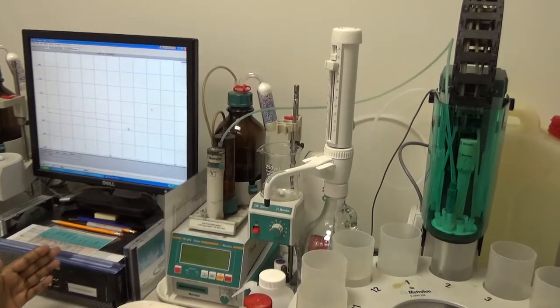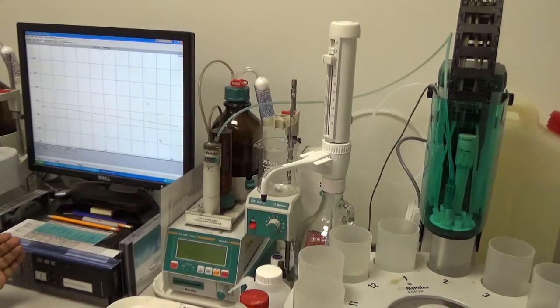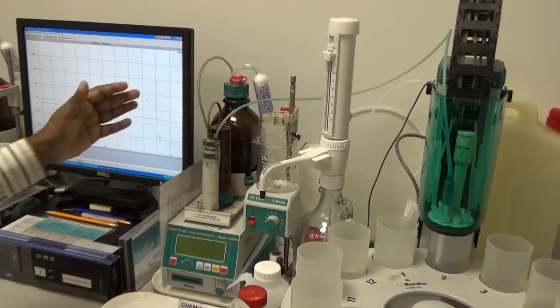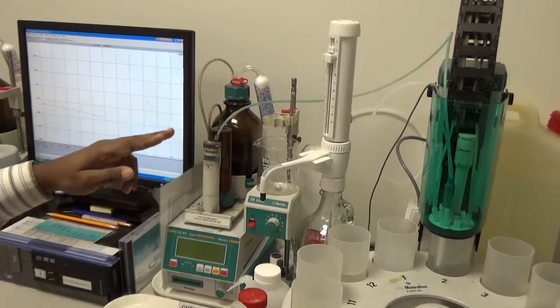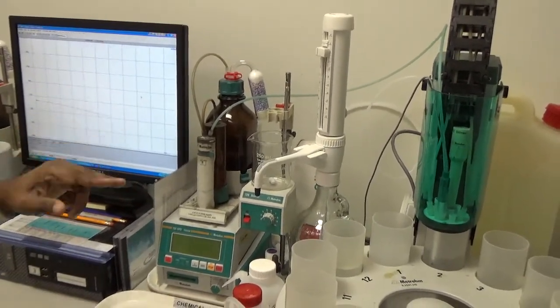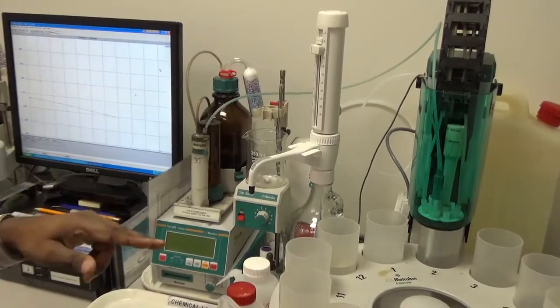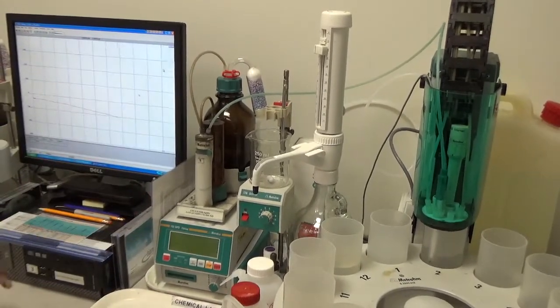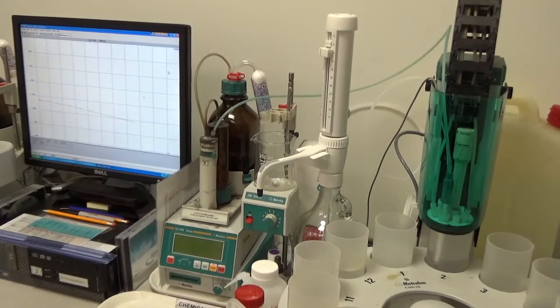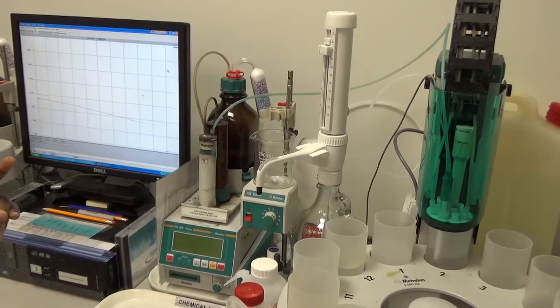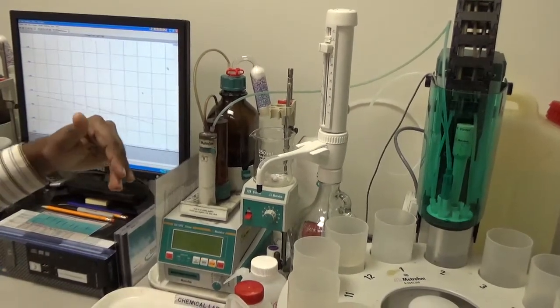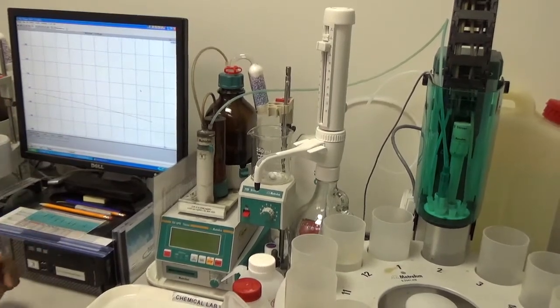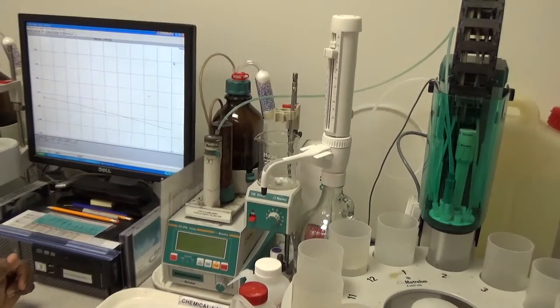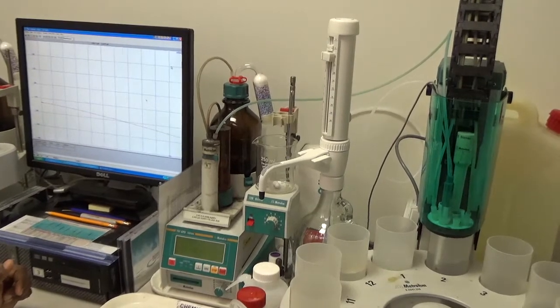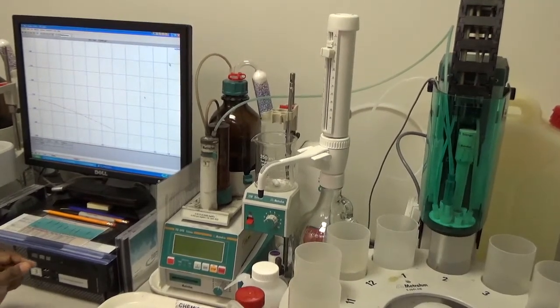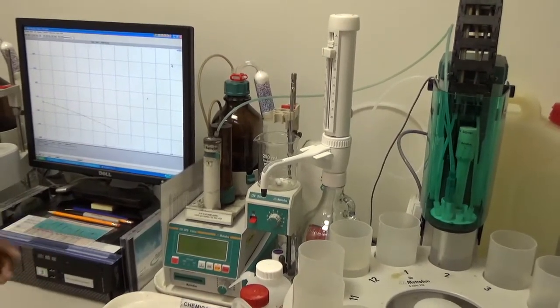Usually the second time is more accurate than the first run, because of some air bubble present in the tubing. That's why we always do the first sample run and then another one before we start adding the unknown samples. We do at least 2 blank samples to clean any air in the passage before we start the unknown sample. So we can accurately determine the chloride content after this calibration is done.